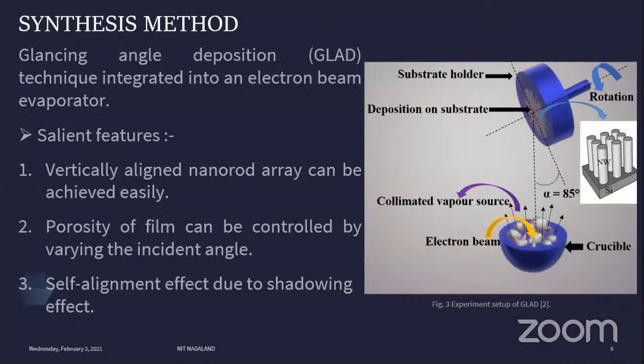Yes, sir. A series of papers have established that in this technique, if we set the angle of incidence of the vapor flux, as shown in the figure here, greater than 80 degrees, we can achieve nanowires or nanorods effectively. But at 85 degrees, the probability of achieving proper nanowires with good porosity is high.